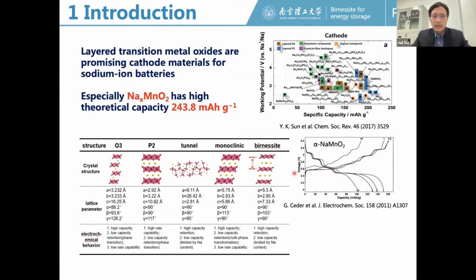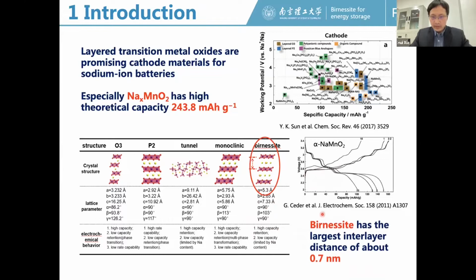And then we notice that there is another type of layered structure, which is called Birnessite. For the Birnessite structure, we have crystal water existing at the interlayer, which can expand the interlayer spacing. And Birnessite has the largest interlayer distance of about 0.7 nanometers.